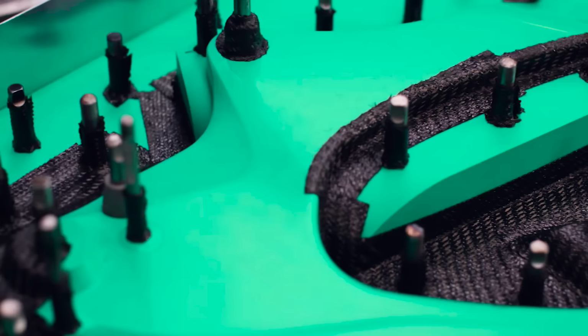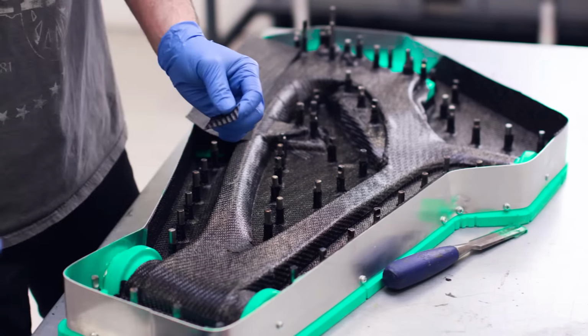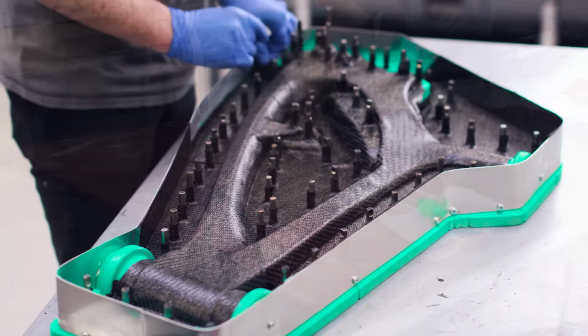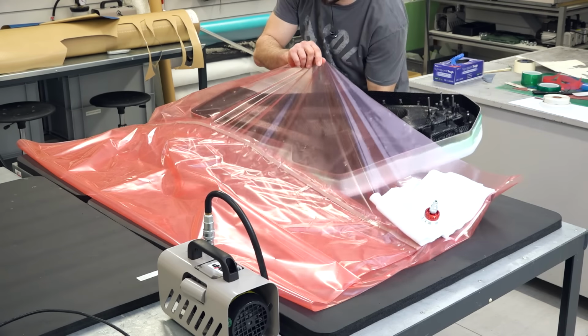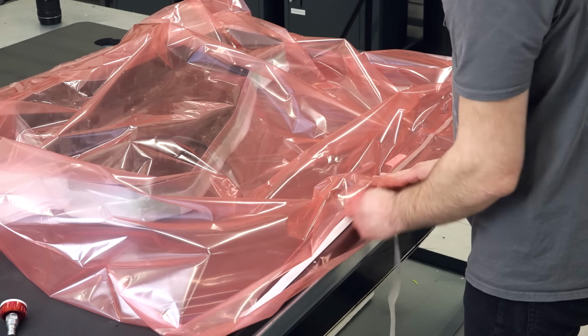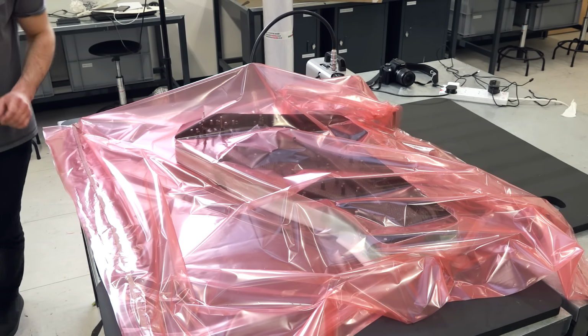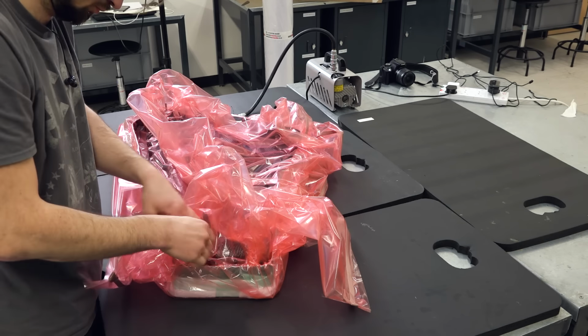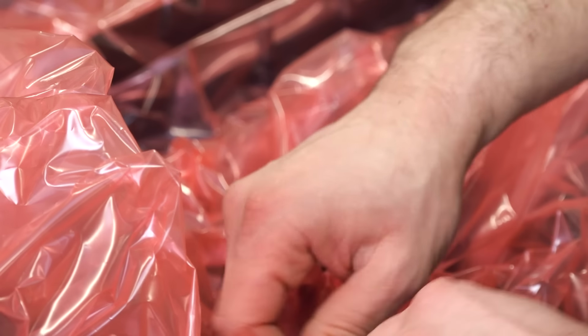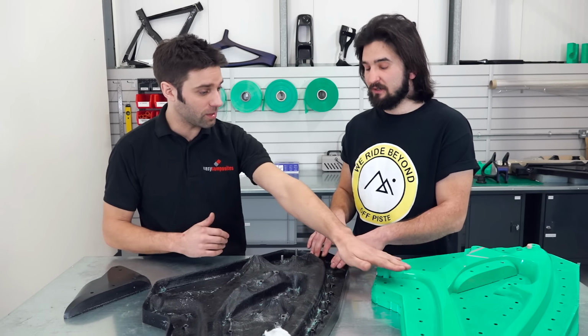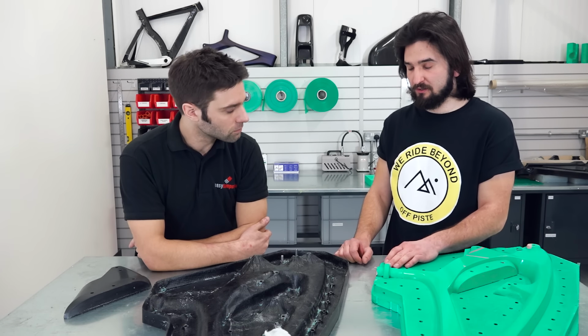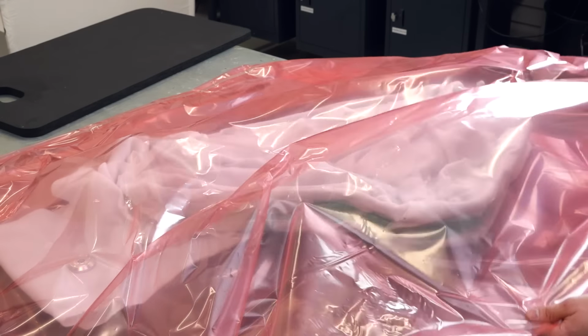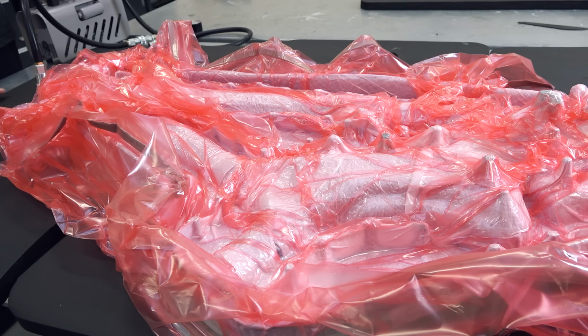Quite some time. And before finishing the first ply, this has all been debulked. Okay. So you debulk after what, between every ply, or? I debulked on the first ply twice, when the corners were in and then when the corners were covered. So this ensures that the first ply stays on. And that actually just helps to tack the mold down. And the second debulk was, I left it overnight. So this makes sure that when I come in the morning, it's all properly stuck to the mold.